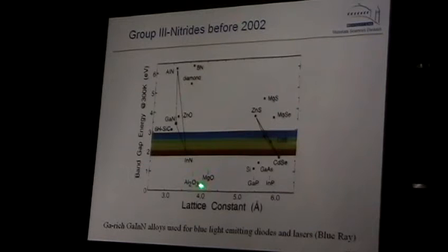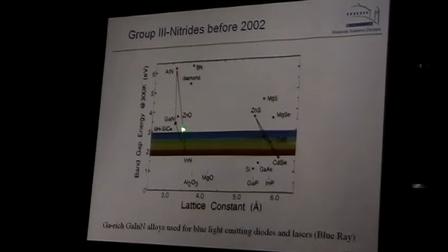Nitrides are compound semiconductors of group 3 elements like indium, gallium, aluminum, and nitrogen. And they have a very interesting property that they span a very large range of band gaps. Aluminum nitride has a band gap of 6.1 electron volts, which is deep ultraviolet. Gallium nitride is close to visible band gap, and indium nitride was a mystery. Nobody knew really what was wrong with indium nitride.